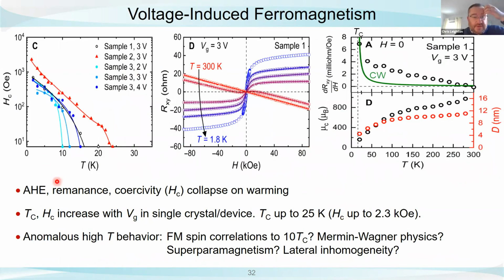And also, you can measure the coercivity as a function of the temperature. Multiple samples here. As we go up in gate voltage, you see the coercivity just dies as we would expect. It looks like the highest TC that we're able to get in this material is about 25 Kelvin, but it's being induced not only from a state that has TC equals 0, but also from a state that initially had spin 0, right? Now, there are certainly things that we don't understand. In particular, the temperature dependence is very interesting. So if we look at the temperature dependence at high voltage, you have this nice anomalous Hall signal. The coercivity disappears at 25 Kelvin. We believe that to be the Curie temperature.